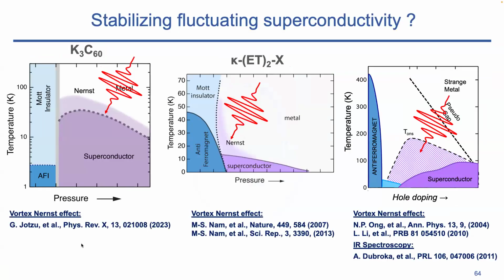The strategy behind this is to take a material, again referring back to Laura's talk yesterday, in which you measure the Nernst effect. As most of you know, the Nernst effect is the measurement of a transverse voltage in the presence of a magnetic field and a longitudinal thermal gradient. There's a quasi-particle contribution to this effect, but if there are vortices present above TC, these vortices will diffuse because of the thermal gradient.